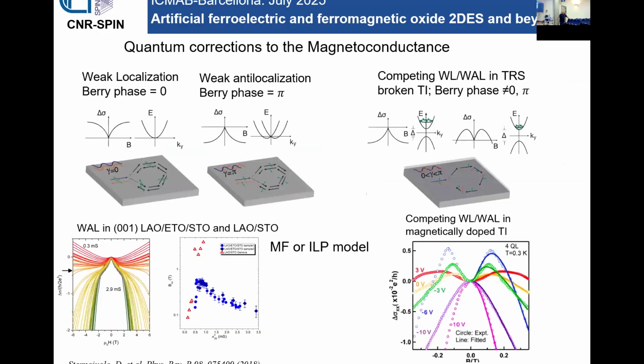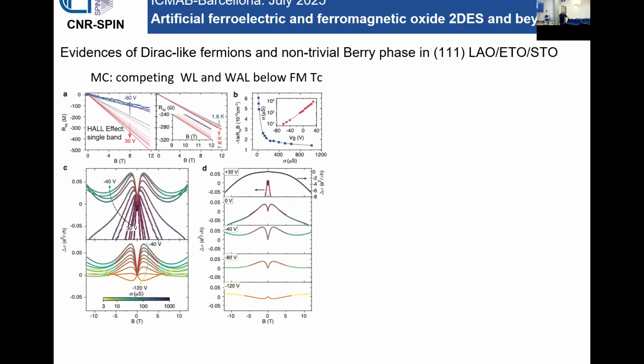And indeed, if you perform measurements on a standard 2DEG, you get classical weak localization or weak anti-localization magnetoconductance, so you can fit very well. While if you look at the literature, for example, at these magnetically doped topological insulators, you start to see this anomaly in the magnetoconductance, which is similar to what I have shown before schematically. So essentially, this weird shape with a maximum at some field. And this is exactly what happens now in the case of our two-dimensional electron gas. So in our oxide two-dimensional electron gas, we saw essentially the same anomaly, which can be tuned by the gate voltage, of course,